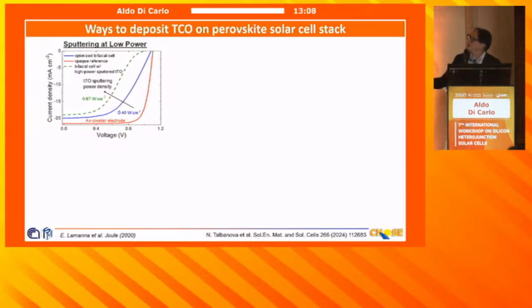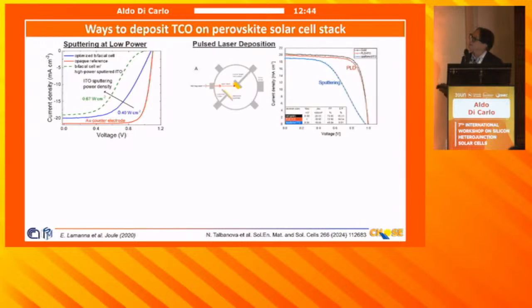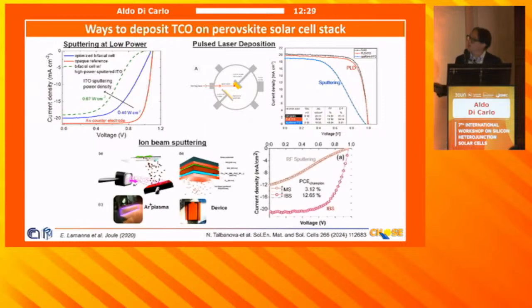For example, in this case, this is the IV characteristic for the opaque cell, and with 0.4 watt per square centimeter we get an IV characteristic which has no S shape, as we get for large power. This is low power still with sputtering, but one can use a different technique, for example pulsed laser deposition. Pulsed laser deposition is quite gentle. With sputtering you have an S shape, while with PLD you resemble very much the characteristic of the opaque cell. Or one can use ion beam sputtering, which we also tested. This is RF sputtering, and this is ion beam. You can see that ion beam is also a very gentle way to deposit the ITO on top of the perovskite solar cell.